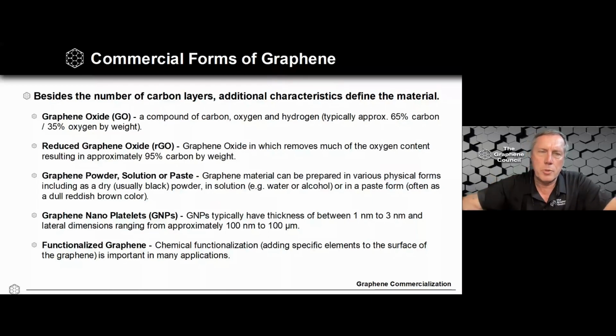Graphene itself might be presented as a powder in a solution or a paste. You also have graphene nanoplatelets, which are stacked a little bit higher than few layer graphene. And finally, you have material that you can functionalize, and this would be adding elements or chemical groups either to the surface or the edges of the individual graphene flakes. And you might do that, for example, to make them bond, maybe even to a glass fiber reinforcement as an example, or in a resin system to aid in dispersing. Next slide.